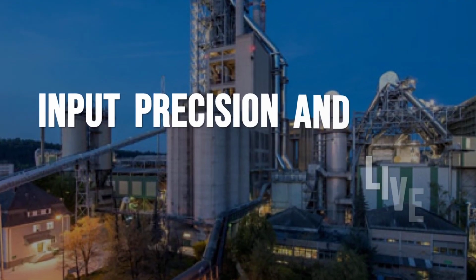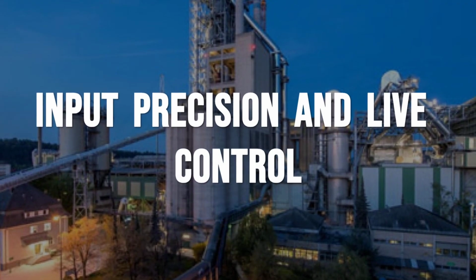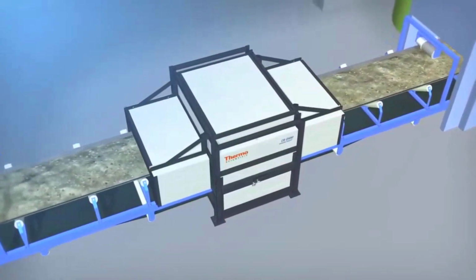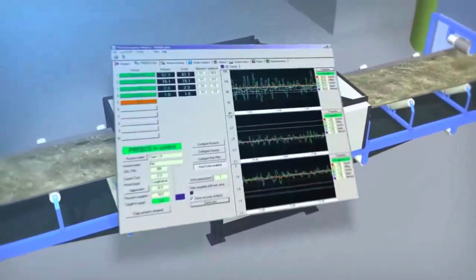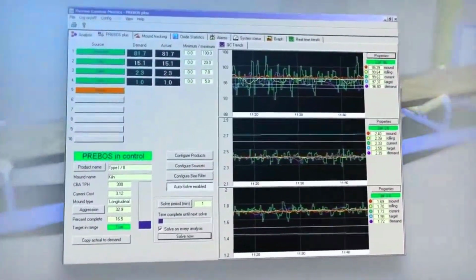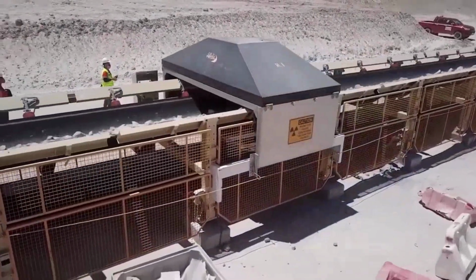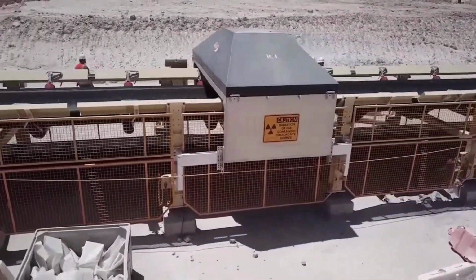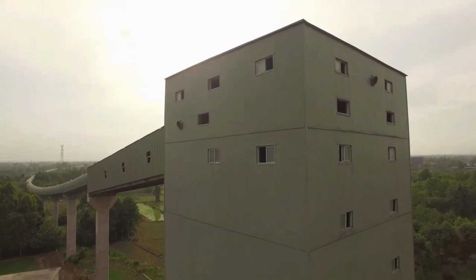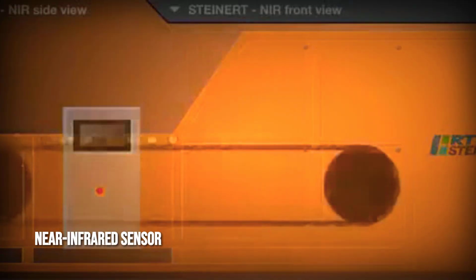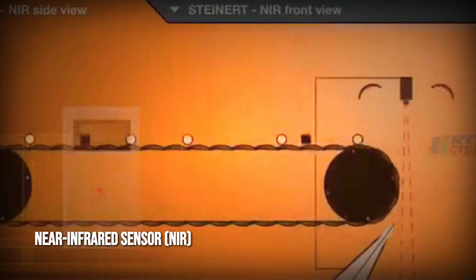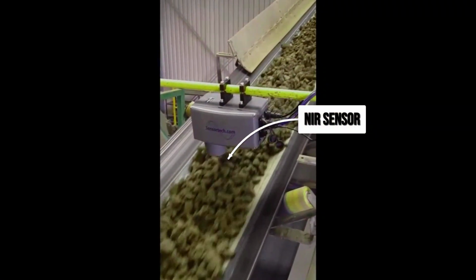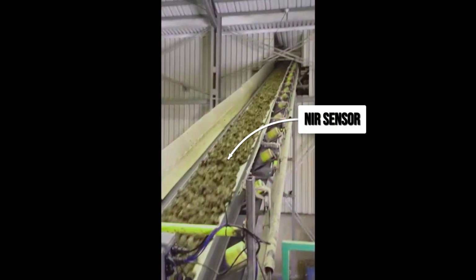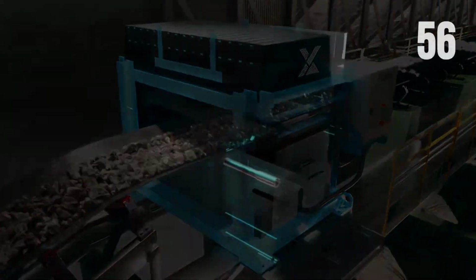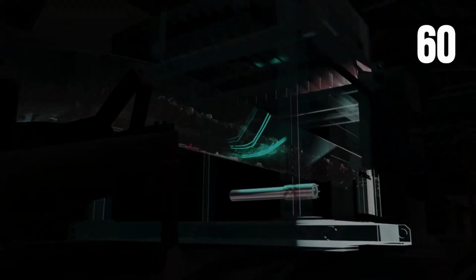At Plant C, the heartbeat of cement production pulses through a network of sensors and control screens. Every minute, Crossbelt XRF and PGNAA analyzers scan raw limestone and clay as they move along wide conveyors toward the blending silos. Near-infrared sensors, abbreviated NIR, are tuned to detect subtle shifts in mineral phases and moisture, and they capture readings in less than 60 seconds.